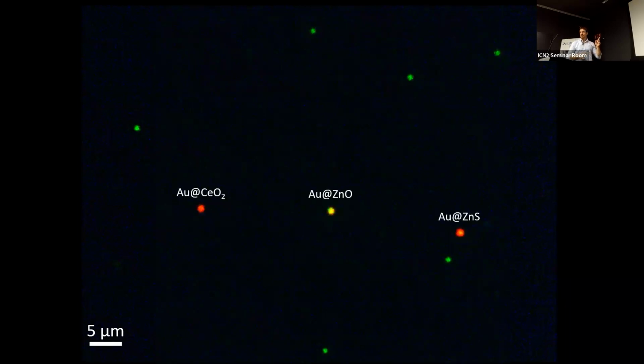So we could grow different semiconductors on the same sample on adjacent nanoparticles. And what I find really beautiful is that, for example, this gold nanoparticle that is sitting maybe 5 microns away from it is completely untouched. Like we're really localizing chemistry on the surface of an individual nanoparticle.